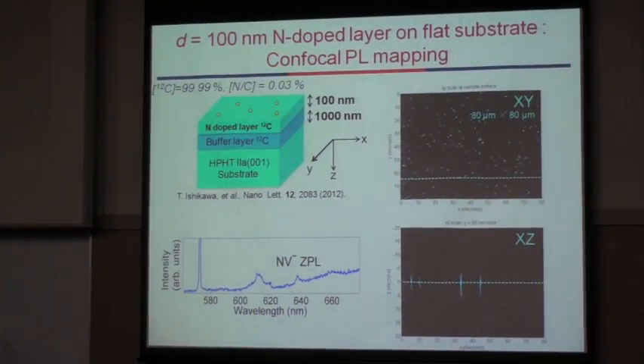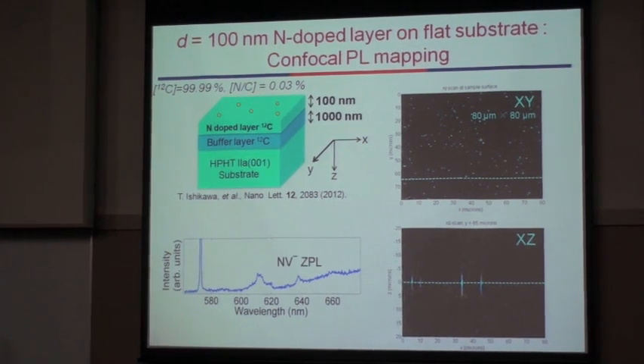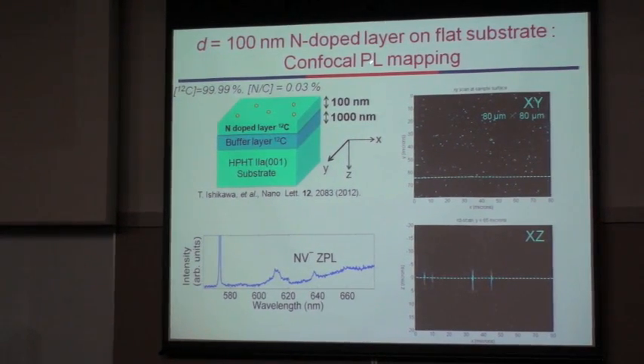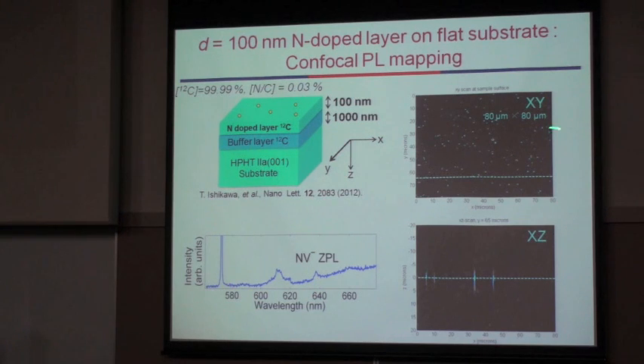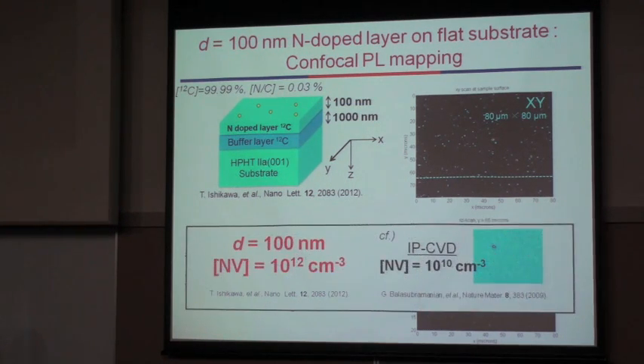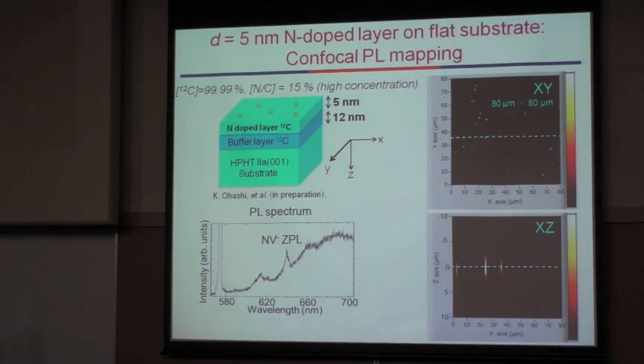So first, we will show you the result of a 100 nanometer nitrogen-doped layer on the flat substrate. This figure shows a confocal photoluminescence mapping of this sample. And we observe many bright spots, which correspond to the single photon emission from the NV center in diamond. So as a result, we can dope effectively in the thin layer on the diamond substrate. After that, we tried to fabricate a thinner diamond layer, which is a 5 nanometer thickness layer.